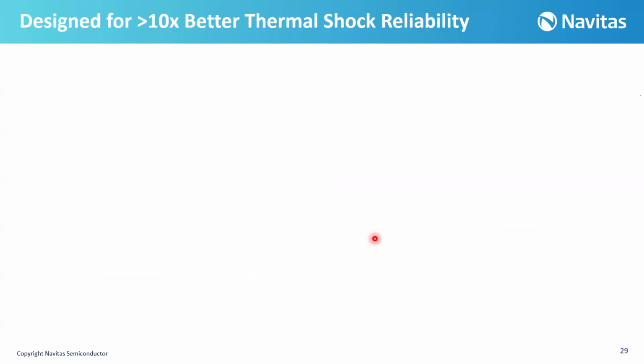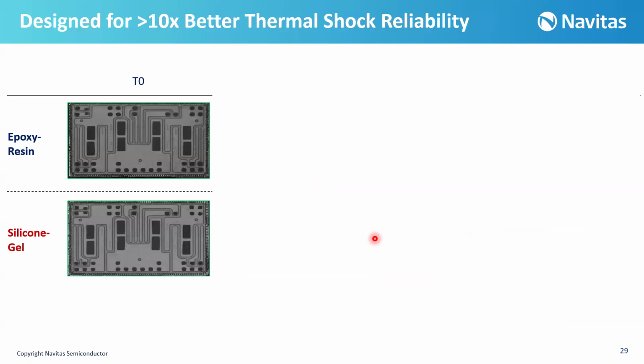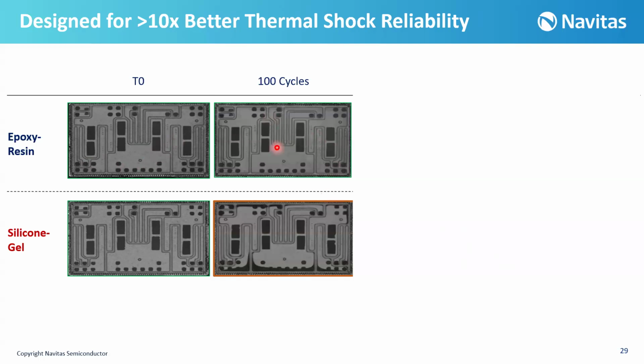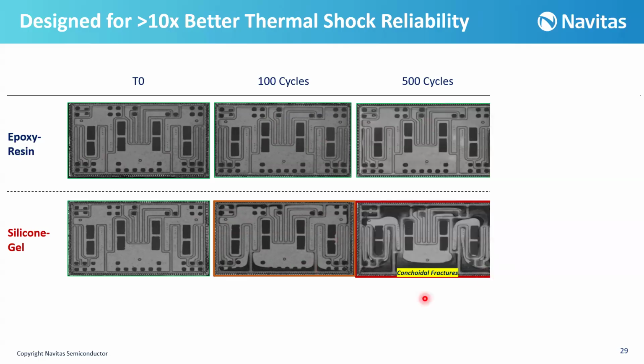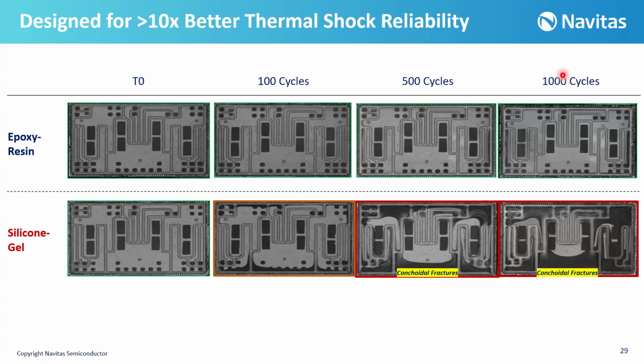As I mentioned, we designed this module in order to have 10x better thermal shock reliability. Now let's compare the epoxy resin with silicone gel in this thermal shock reliability test. Here is the DBC picture at time 0. After 100 cycles, as you can see, there is nothing in the epoxy resin. But if you look at the silicone gel, you can see some degradation on the DBC. Now, after 500 cycles, we can see conchoidal fractures in the silicone gel, but just a little bit at this part and this part with the epoxy resin. And finally, after 1,000 cycles, you can see a lot of conchoidal fractures with the silicone gel. But again, only a few parts here are affected with the epoxy resin.